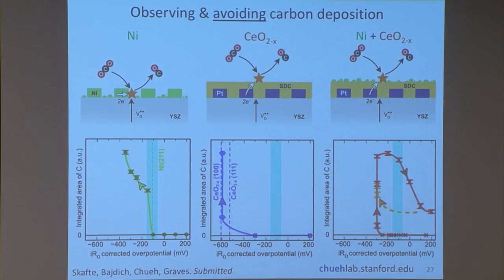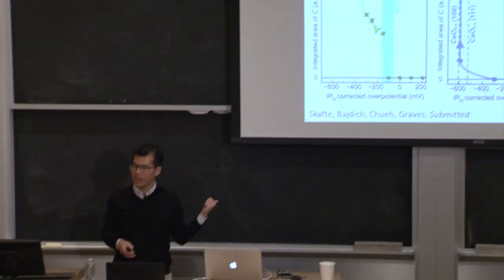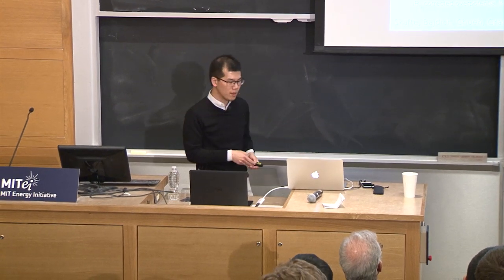So there it's about halfway, so you can push beyond the equilibrium potential by about 200 millivolt, which means now you can operate your electrolysis cell without carbon deposition, making only carbon monoxide from CO2, which can subsequently be used in a process to synthesize carbon-containing fuel renewably, and you can operate it with 100% selectivity as long as you stay below this threshold. So this two picture shows you what is currently done and what may be possible. And we're trying to gain the fundamental insight through this characterization, and also show next also through modeling as well.